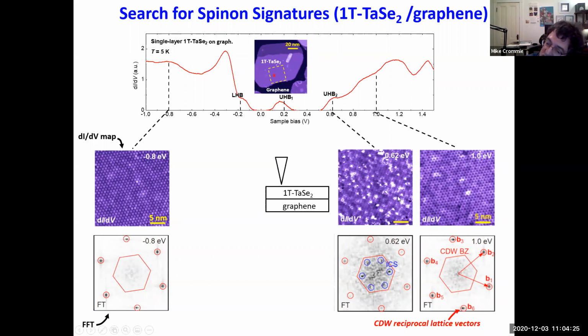And now you can see from the dI/dV image that at this energy, the local density of states looks totally different. You look at these two images, they don't look the same. At the upper Hubbard band, we see lots of these long wavelength features. You can see it with your eye. And it looks pretty disordered, but when you do a Fourier transform, you see that there are some well-defined periodicities living inside of this image.